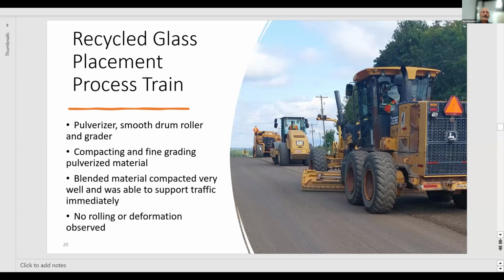Here's the recycled glass placement process train: the pulverizer, smooth drum roller, and grader, compacting and fine grading the pulverized material. Blended material compacted very well and was able to support traffic immediately. No deformation or rolling was observed.